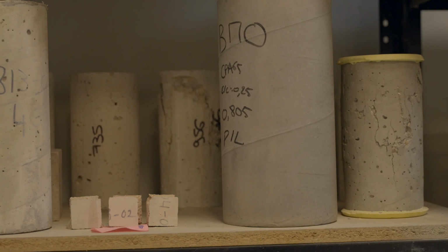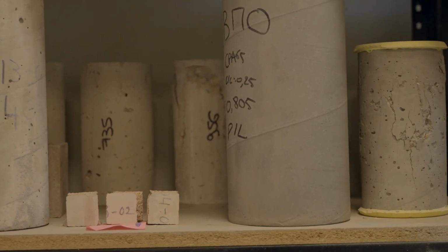After 24 hours from making these specimens, we demold them and can either store them in the curing room or test them if the test is scheduled for 24 hours.